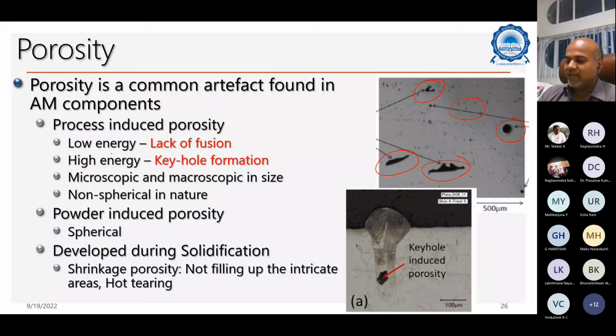Okay, the small pores are actually from low energy and lack of fusion. Otherwise, these small pores are coming from the particle quality, and these are coming from the lack of fusion. If the laser power intensity is not good, if the temperature flow is not uniform, then it leads to certain kinds of defects. Okay, with keyhole formation, lack of fusion. So this is what actually is the process induced porosity.